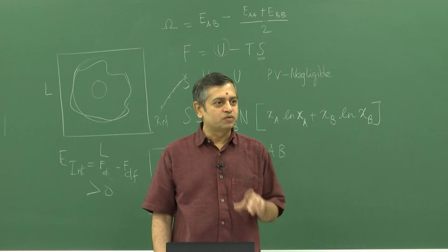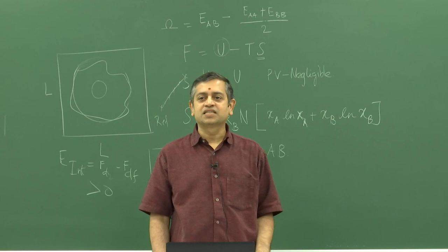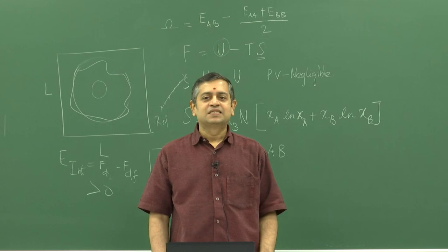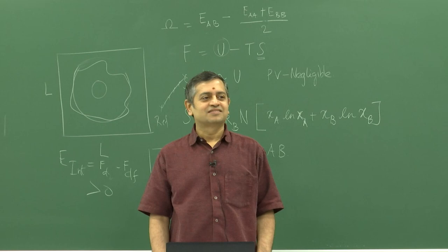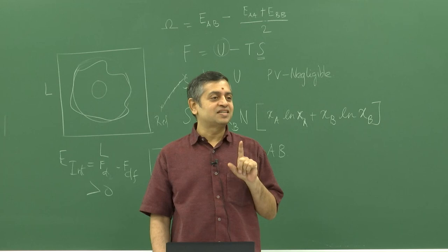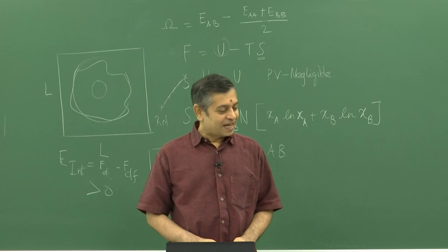I just want to leave you with one question though. Let us say pure copper, and I want to calculate the stacking fault energy, which is 40 millijoules per meter squared. Now I have a simulation cell where the stacking fault area will be on the order of nanometers squared. How accurate should my free energy evaluation be so that I can get a meaningful stacking fault energy? That is something for you to think about.